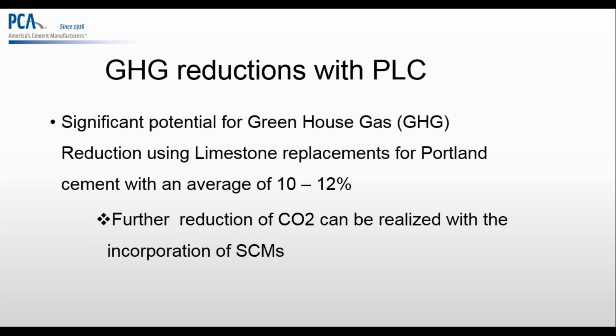The PLCs can provide us some significant potential greenhouse gases reduction, at the rate of 10 to 12% if they are used properly. And you can even achieve greater reduction in the carbon dioxide by using SCMs, right? When I say SCM, it is supplementary cementitious material like slag, fly ash, metakaolin, pretty soon calcined clays, ground glass also, that is becoming a little bit more popular. It still has a lot of work to be done, but that's a very good product as well.